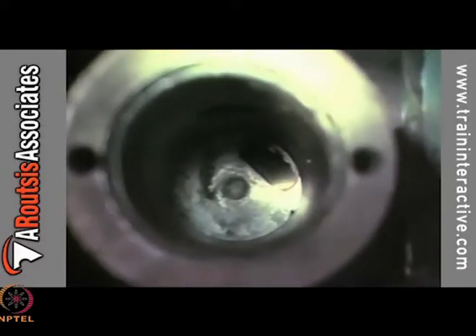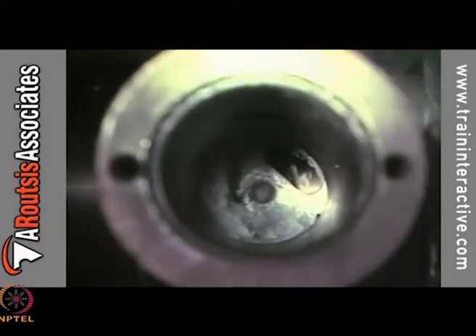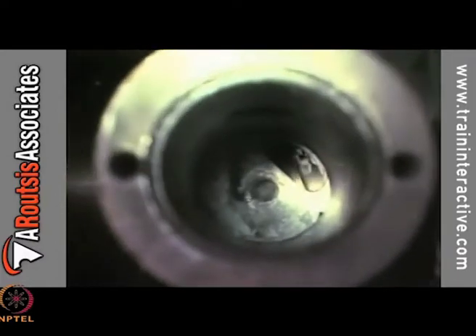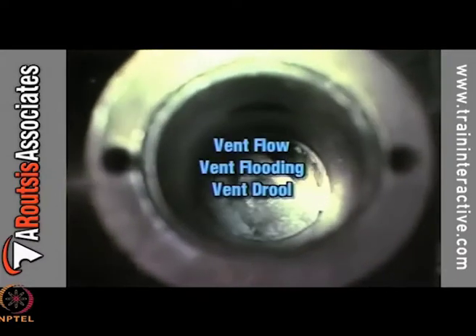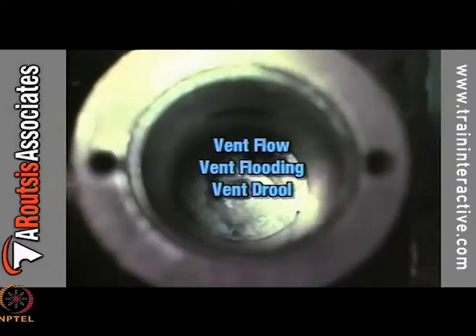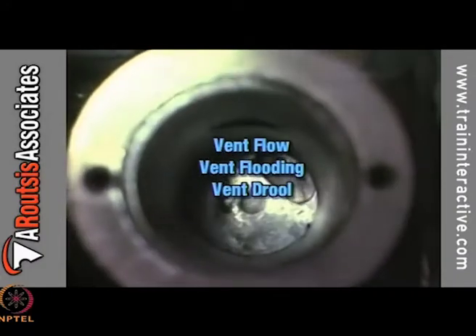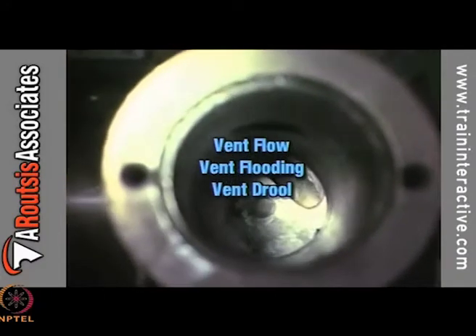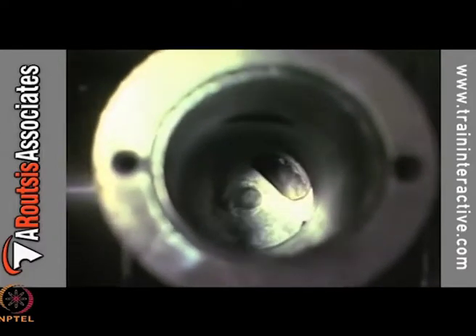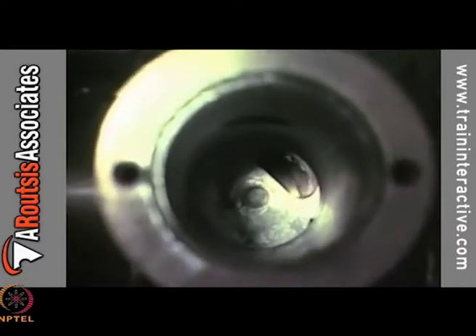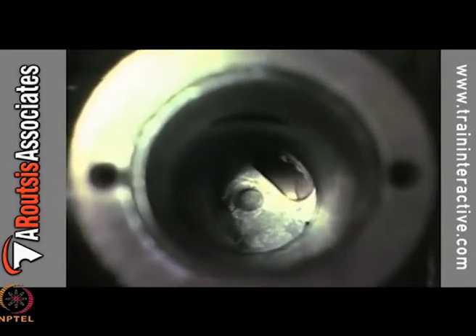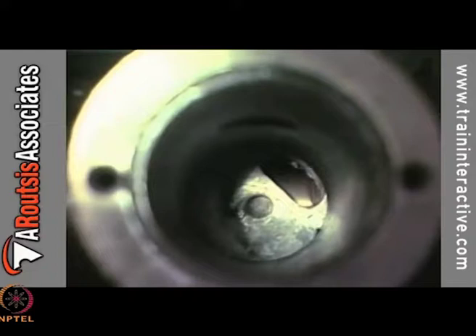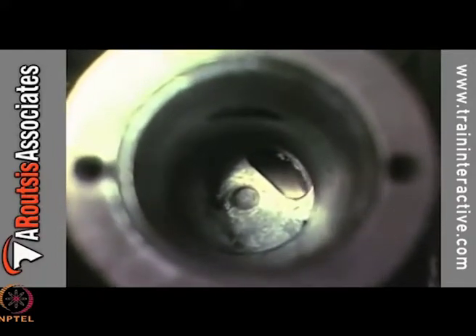Whenever the processing conditions permit material to move into the vent section at a faster rate than it is conveyed out, material may flow out of the vent. This is vent flow, vent flooding, or some other descriptive term. In counter-rotating extruders, high melt pressure ahead of the screws is one cause, especially if the screws are worn, but there are many others. In co-rotating extruders, vent flow can be related to the screw design, screw wear, feed rate, screw RPM, and other factors.